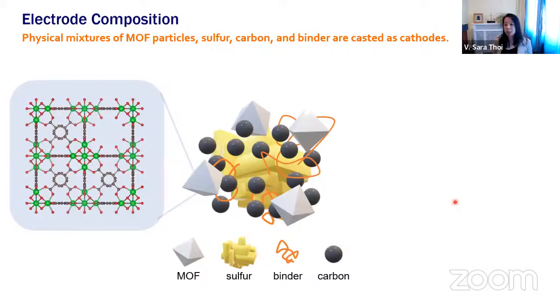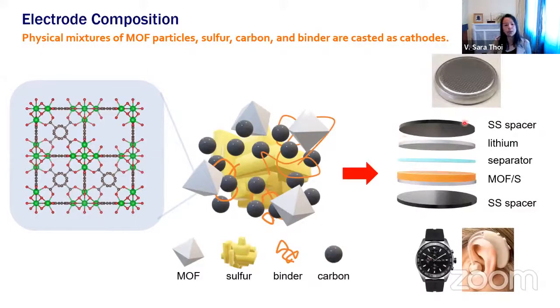But with all that, we wanted to know if this works. And so we did a very simple, unoptimized electrode material where we take the metal organic framework, combine it with sulfur, with our binder, which is PVDF, and carbon, and we casted it onto a simple electrode, two-dimensional, onto a coin cell for us to do the testing.